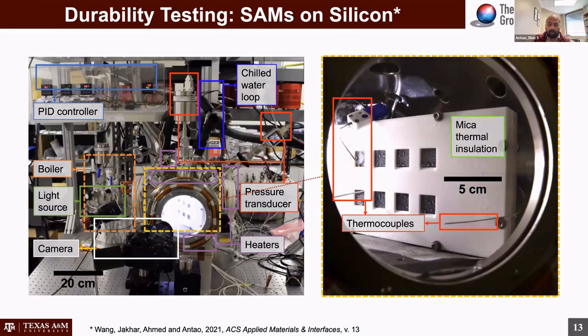The next step was to throw it into a test chamber and to actually condense on it. And in fact, we spent a lot of time building this test chamber, not because it's difficult to make a vacuum chamber, but because we were careful about identifying all potential sources of leaks in the system, and because we wanted to do the experiment in the most pure environment possible. And so we spent a lot of time developing degassing methods, as well as ensuring that there were no non-condensables in the system when we were operating. Because if there are non-condensables in the system when you're operating, then we may not be able to come up with the right hypothesis, because we have potential for air interacting with the silane also, which adds an additional variable in the system, which we don't want.